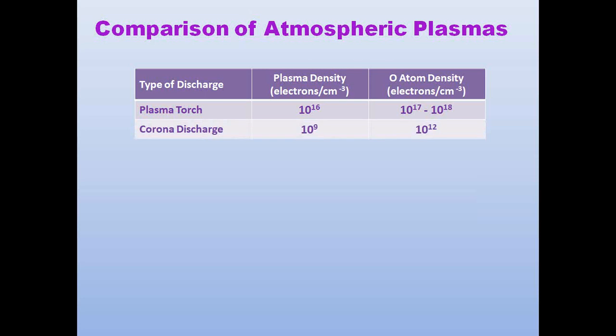That gives you these types of densities. In comparison, an air plasma or a corona discharge will have less electron density relative to the plasma torch, as well as less oxygen density. Why is that? Well, the reason is because we are not forcing any type of airflow or gas flow to the surface. In this case, we are reacting ambient air, mostly ambient air, at less than high velocity, or less than the velocity of a plasma torch, and ultimately you have a reduced density.